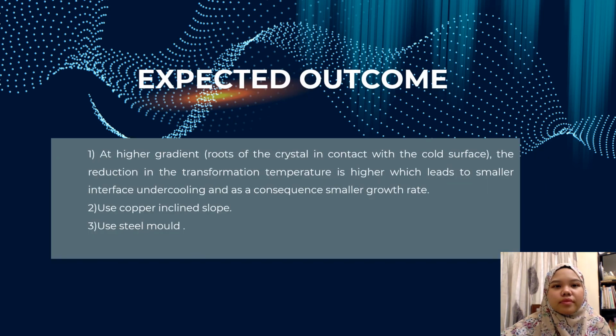Okay, and the expected outcome from this project is that at a higher gradient, the roots of the crystal in contact with the cool surface have a higher reduction in transformation temperature, which leads to smaller interface undercooling, and as a consequence, a smaller growth rate. And then we'll be using a copper inclined slope for the cooling slope casting process, and also use the steel mold.